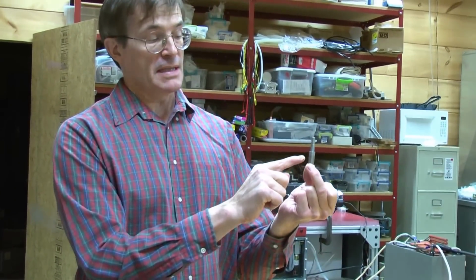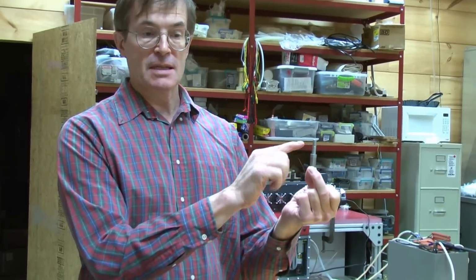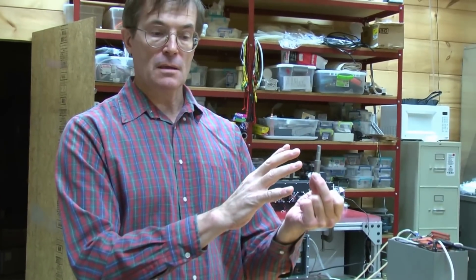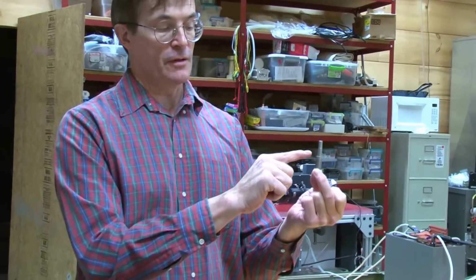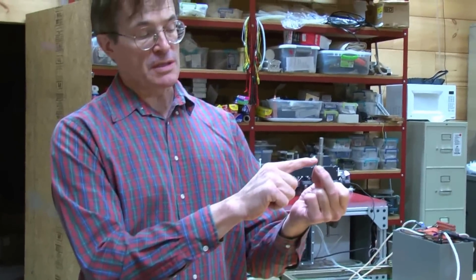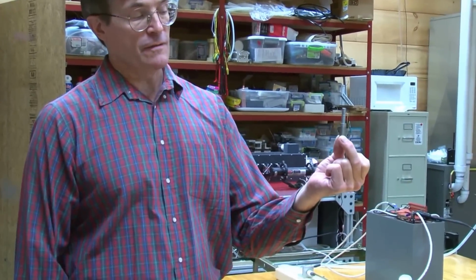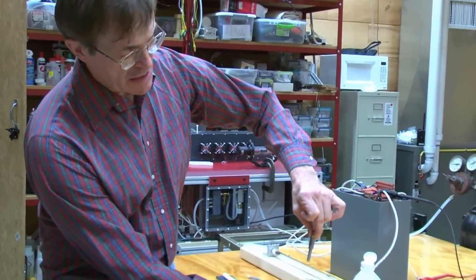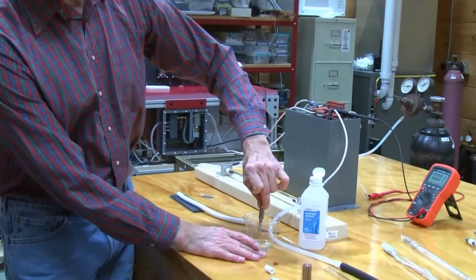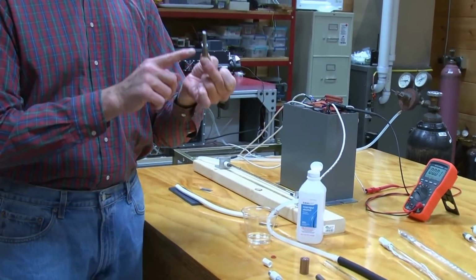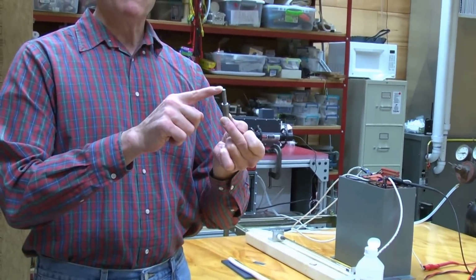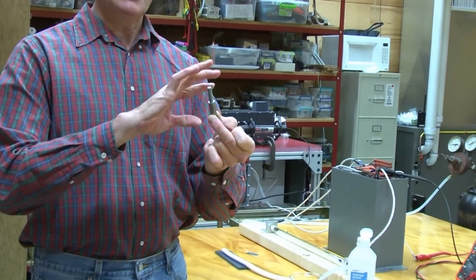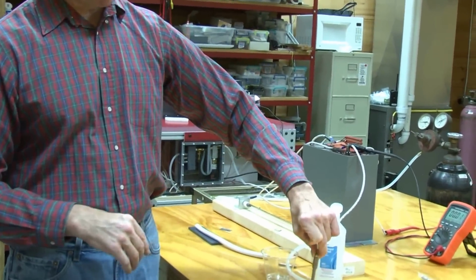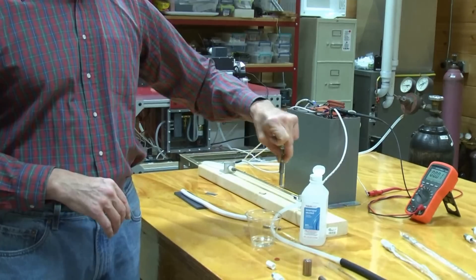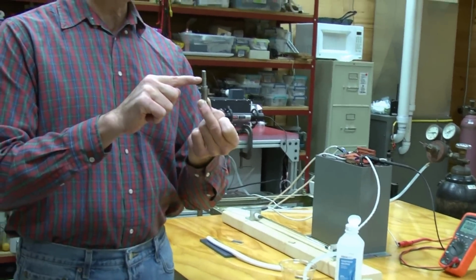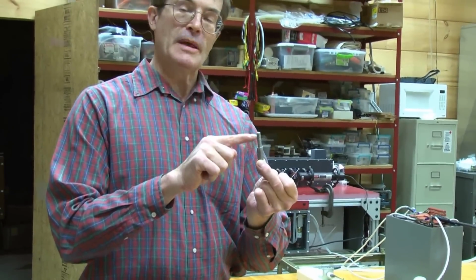And the problem with this is that the copper that's on the outside of this will ablate under the high loading of the flash lamp. So what I do is, if you can see the color distinction here, when it's all finished, I'll dip the end in a cup of concentrated nitric acid for about 3 or 4 seconds. You'll see blue foam come off of the end of the electrode, and then it stops. I'll take it out, rinse it off with a little bit of distilled water, and put it back in the cup. After about 3 or 4 iterations, the foaming stops.